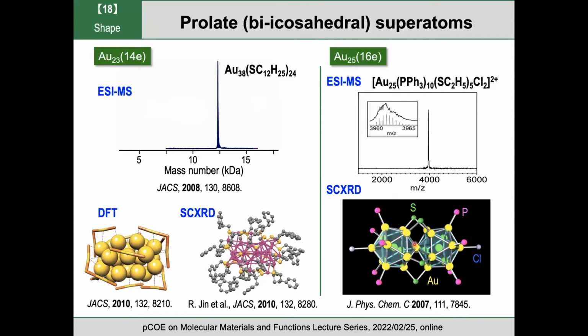And in this case, we can see this dimer as corresponding to a rare gas dimer, because 16 is double of 8 electrons. So the electron shell is closed with 8, and they weakly bind together to form this dimer. Okay, then what about this structure, 23?